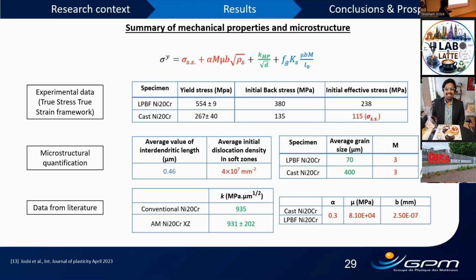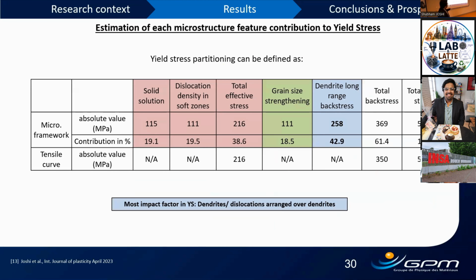So using all the values in this equation, we can actually quantify the effect of all the microstructural features. Starting from solid solution and dislocation density in soft zones, the combination of this prediction is 216, and this is exactly what we get from experiment. It's a perfect match. I think I should have stopped doing the PhD here. 0% error, but unfortunately life doesn't go like that, so we move on.